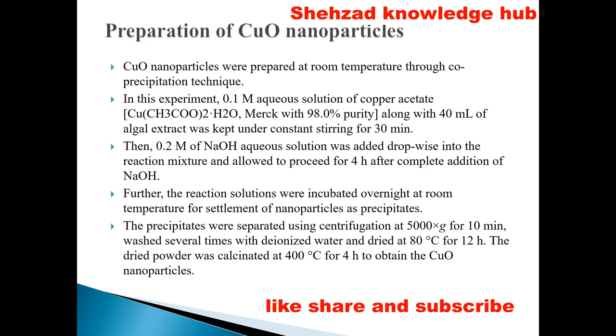Preparation of copper oxide nanoparticles. Copper oxide nanoparticles were prepared at room temperature through the co-precipitation technique. In this experiment, a 0.1 molar aqueous solution of copper acetate along with 40 ml of algal extract was kept under constant stirring for 30 minutes.